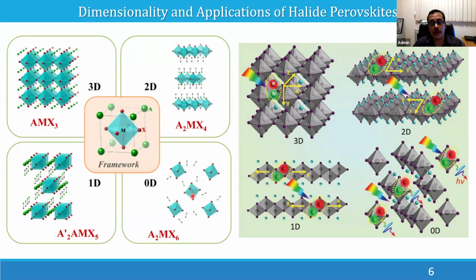This is a real quantum confinement effect. These excitons are confined in the octahedral structure. They cannot travel, so what they will do is recombine easily, and that results in light emission. So if you want a light-emitting material, instead of going for 3D, it is better to go for a lower dimension, particularly zero-dimensional perovskite.